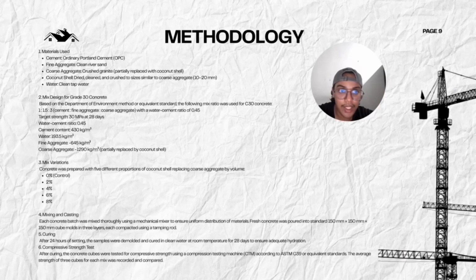And so for our mix design for grade 30 concrete, based on the Department of Environment method or equivalent standard, the following mix ratio was used for C30 concrete: 1 to 1.5 to 3. 1 for cement, 1.5 for fine aggregates, and 3 for coarse aggregates. There's also a water cement ratio, which is 0.45. Okay, so for target strength, it is 30 MPa at 28 days. And for water cement ratio, it is 0.45.